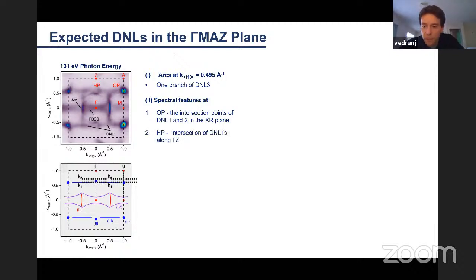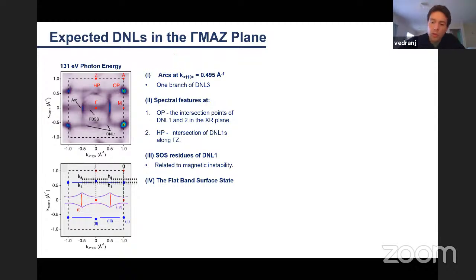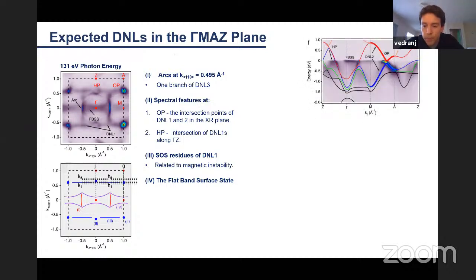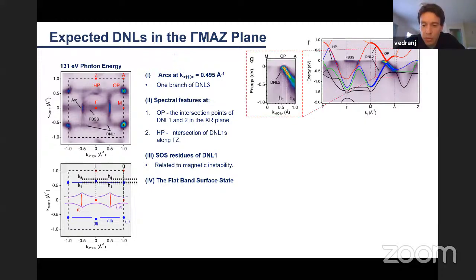And then you see this fuzzy horizontal streaks connecting points OP and HP, and they are spin orbit split residuals of this third Dirac nodal line. And they actually form these hot streaks, which I'll show you in one of the later slides, claimed to be responsible for the magnetic instability in the material. And fourth, you can see these two prominent arcs spanning between features 1, and they're the signature of the flat band surface state. So the ARPES band structure along the high symmetry planes is well reproduced by the DFT plus spin orbit band structure calculation, following the discussion by Jan Soon on the previous page. And we can then identify these intense features in the Fermi surface.